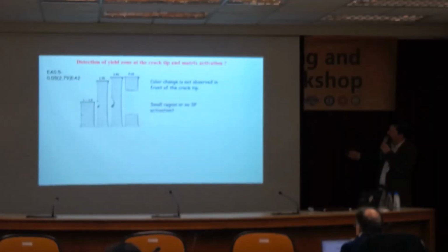Now, another point is, can we still detect the yielding at the front of the crack tip? I saw before that indeed we can detect bond breakage, random bond breakage. We don't know where it is, but we identified in the previous experiment that there was some kind of yielding, but in uniaxial extension. What of a material that doesn't yield in uniaxial extension, but could it yield at the crack tip? So we tried to do the experiment with the mechanophore in the second network. So it needs to be activated to see anything. And we put it at the crack tip, and unfortunately, we didn't see anything. So there was no color change in front of the crack tip.